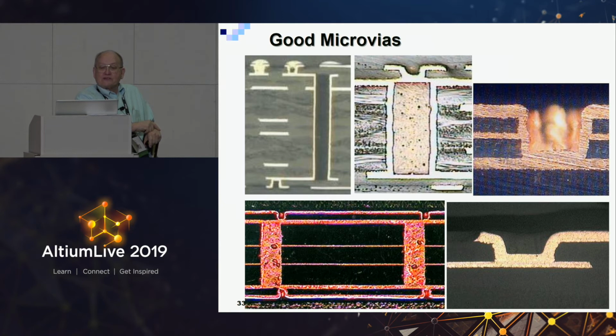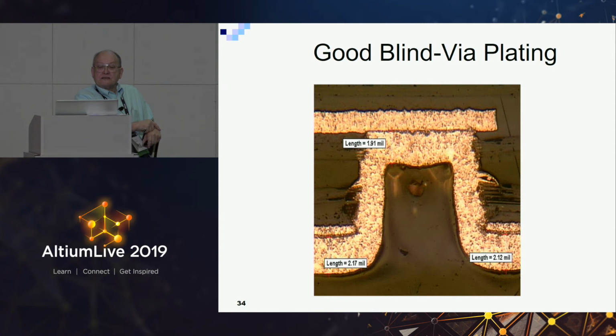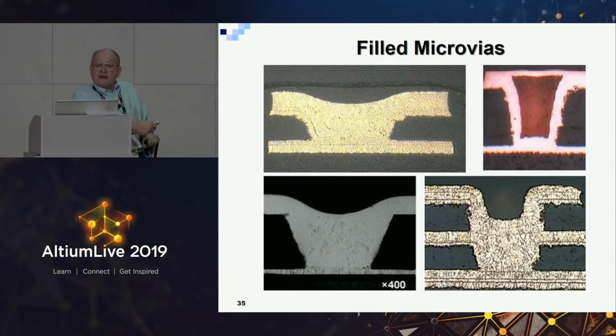These are just different pictures of good microvias that are properly plated and designed and positioned. There's good blind via plating, it's kind of uniform. It's not collapsed. This is good filled microvias, in which, see, that's totally filled with the different chemistry that will fill that up, solid copper. This one is filled with a dielectric and then capped over. This is okay, but this costs a lot.